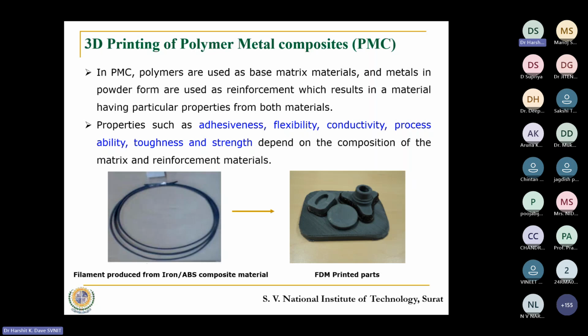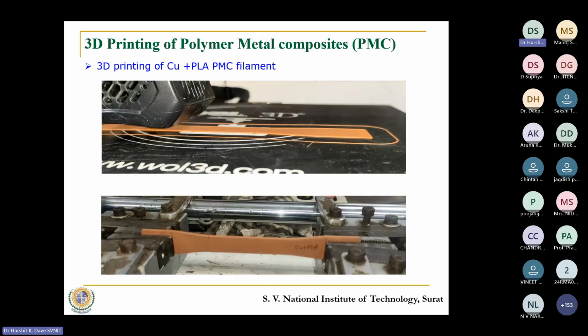So that is how metal is being attempted, by mixing it into a selected polymer for creating a filament for the FDM process. Of course, the nozzle that you use with, say, an open source FDM machine has to be specifically kept for this, because once you use it, it does not become useful for neat polymers. We would observe some sort of wearing inside, and then it may not result in exact 1.75 mm for a usual polymer filament. We have attempted creating some parts with copper addition,